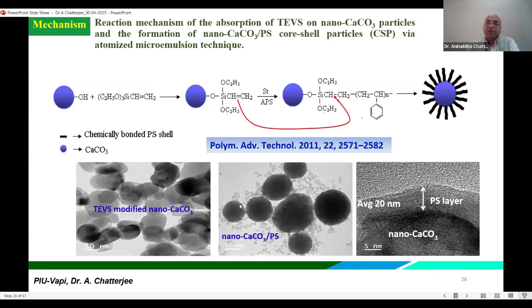Here you can see the nano calcium carbonate with a polystyrene layer. Here you can see the average 20 nanometer layer grafted on the surface of calcium carbonate nanoparticles. So basically, it's a chemical process. The polymeric layer is chemically grafted on the surface of nano calcium carbonate through a silane coupling agent, that is triethoxyvinylsilane. It is a chemical process where small nano polystyrene chains are anchored on the surface. Here you can see over here.